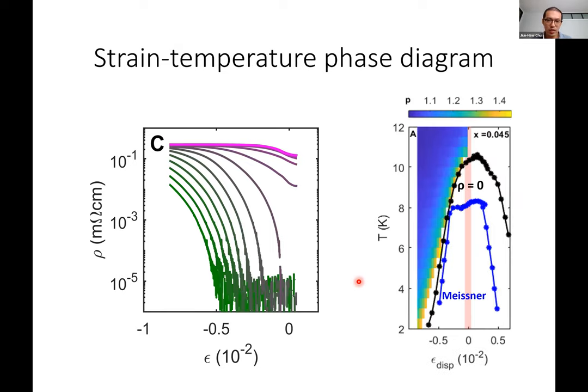Okay, so with all these data sets, we compile the phase diagram of these underdoped samples, where this blue boundary is the Meissner state, which is enclosed by this black boundary, the zero resistance state. Outside the zero resistance state, there's a region where the IV curve is still nonlinear. So we characterize the IV exponent in this color map, where you have an exponent different from one close to the zero resistance state. Eventually, when you apply enough strain or go to high enough temperature, you're fully back to the metallic state with linear IV.